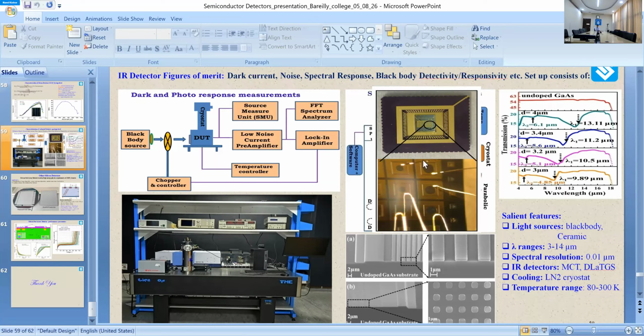After that, we dice the detectors and package them in these kinds of packages. We use these setups and characterize them. We typically use wavelength ranges from 3 to 14 micron, with a spectral resolution of typically 0.01 micrometer. We use two different detectors, MCT and thermal detectors, for the measurements. We use cryostats for cooling the detectors, and the temperature range we normally use is 80 to 300 Kelvin.